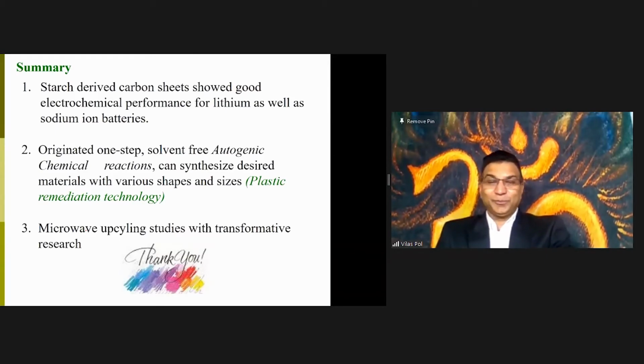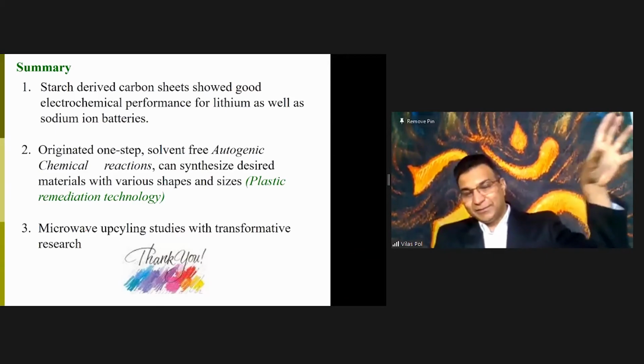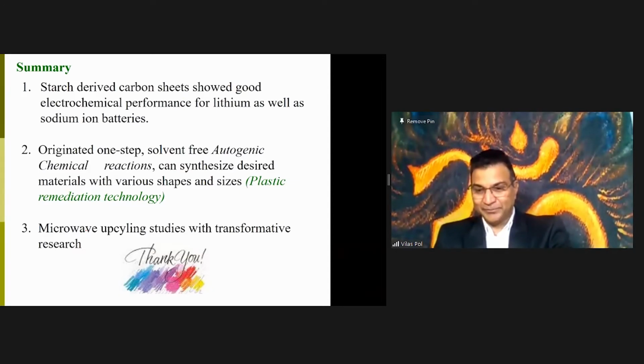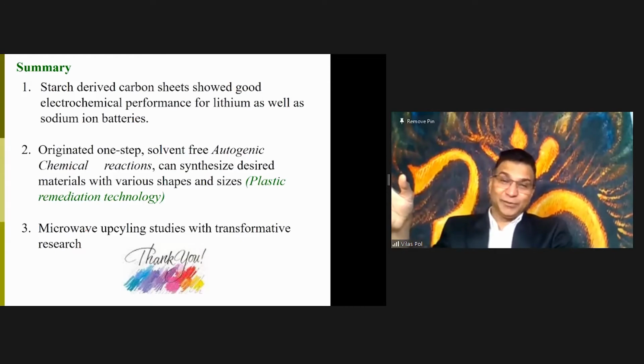But it is not the foolproof solution to your polystyrene-based plastic. Because it is still robust. It can hold the Coke. It doesn't degrade with the Coke. Otherwise, it should really degrade. Coke has pH 2, but it doesn't degrade. That means it is robust with pH and heat.